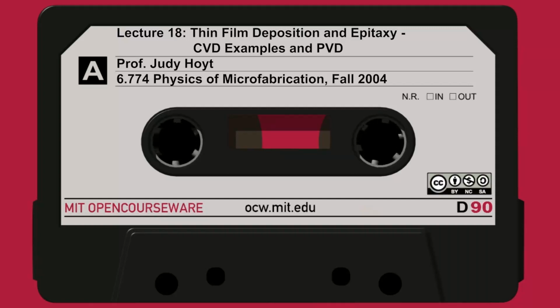Very large grains. In fact, if you take a thin film course in materials science, one of Carl Thompson's courses or whatever, you'll study the thermodynamics of this much more carefully. But basically, it turns out that the grains tend to grow laterally to about the same size as the thickness of the film. The thickness of this film was about 0.5 micron, and the average grain size ends up being, in these large grain films, about 0.5 micron. So the presence of a dopant, phosphorus, really accelerates the grain growth, and you get a very different morphology film.